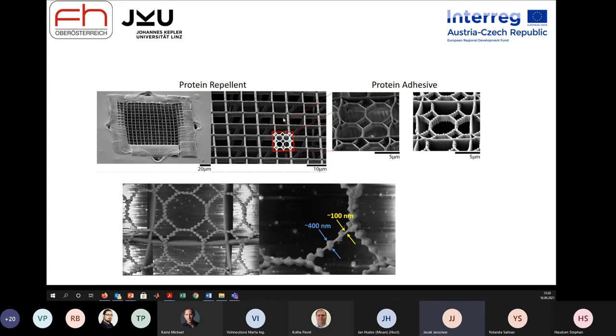At the beginning we were trying not to write 3D structures, just 2D structures, but what we experienced is that the cells really like it when it's 3D, so we had more cells crawling into these holes and interacting with the upper layer of cells when there was a 3D structure in between. And we also varied the geometry. Here you nicely see the one area we filled up with sub elements, and the sub elements were in the range of 100 nanometers.